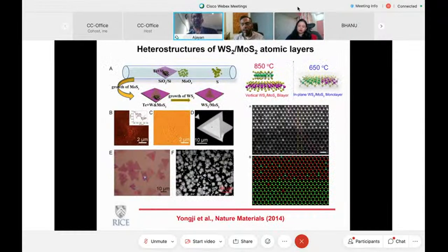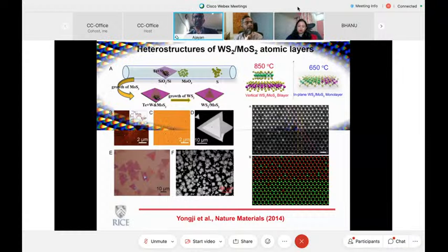Or at lower temperatures, you start to see these atomically sharp lateral heterojunctions. You can see that the junctions are atomically sharp. And if you look at higher magnification, you can also see that. But again, the question about stability of some of these interfaces is very interesting. There are electron microscopy studies to see how atoms diffuse across these two-dimensional interfaces. And obviously, you can see in the image that there is certain diffusion of heteroatoms.